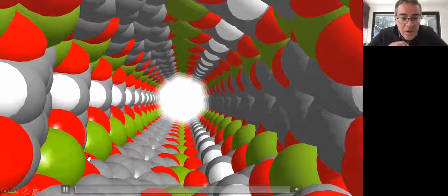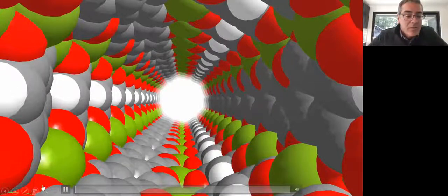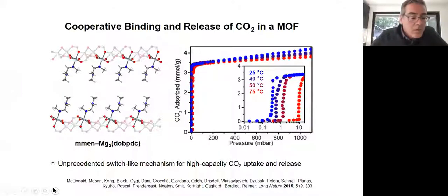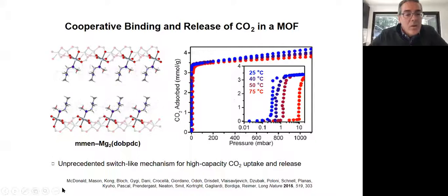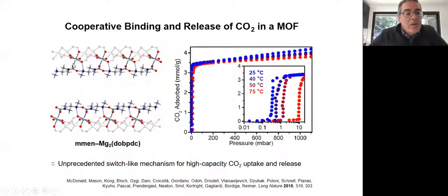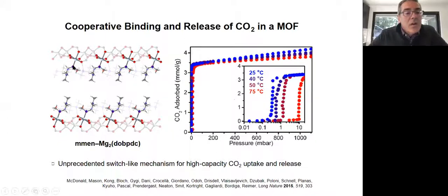And so you're going to have rows of metals with diamines attached. And it turns out that creates a material that shows cooperative CO2 adsorption. And the way it works is CO2 is actually inserting into the metal amine bonds. And when you do that insertion, you transfer a proton from the backside of this nitrogen on the bound amine